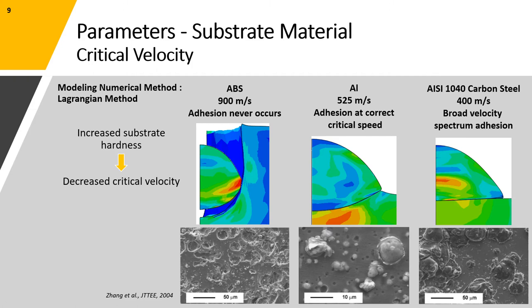And finally, for the hardest one out of all the three, which was a 1040 carbon steel substrate, we observed a successful adhesion at a relatively low critical velocity, equal to 400 meters per second, and also a successful adhesion at a broad spectrum of the particle velocity.